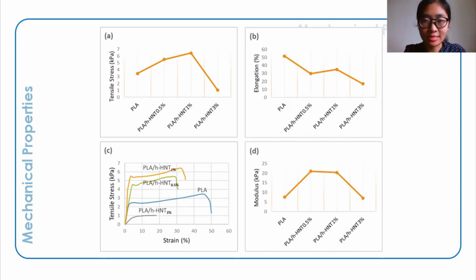A wound dressing material needs sufficient tensile strength and elastic property to withstand stresses exerted by body parts. Hence, tensile strength and modulus can be connected to the conformability of the wound dressing material. The tensile strength and modulus of 1% HHNT content were observed to be the highest and most favorable reinforcement for the polymer matrix. Hence, the reinforcement of hydroxylated halloysite slightly enhances tensile strength and modulus initially at 0.5% and 1%, and then diminishes as clay content increases.